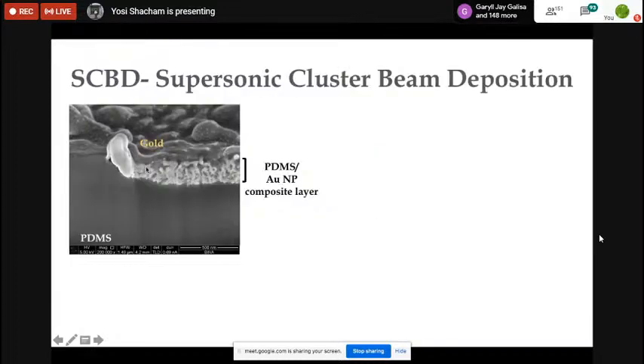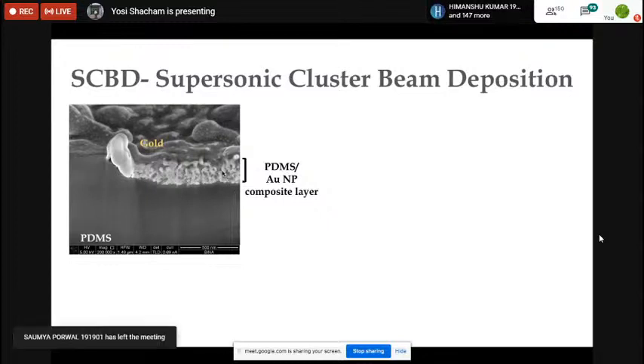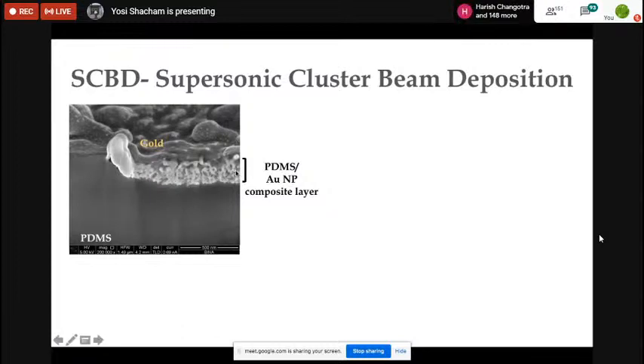And this is how it looks. This is a supersonic cluster beam deposition. This is PDMS, the polymer. And you can see if you implant enough gold, this is the PDMS with gold nanoparticles. It's a composite material, a porous material. It's approximately 50% gold, 50% PDMS. But you can see that the gold, and you can even make it more.